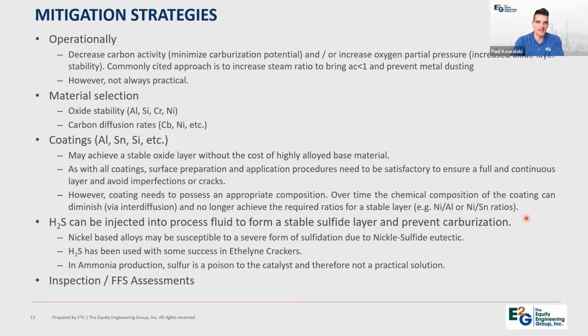And then finally, again, as with many damage mechanisms, inspection coupled with fitness for service assessments may help extend the life of the asset, and FFS may be able to qualify the asset for continued service. Of course, this is likely more reserved for lower damage rates. If in a particular case the metal dusting rate is 1,000 mils per year or higher, FFS likely won't be able to qualify that. It's just going to fail too fast. But if it's a slightly lower damage rate, FFS may be successful in qualifying the equipment for future service.